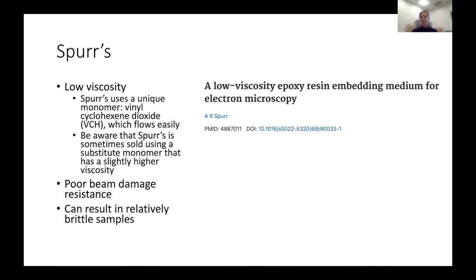So if low viscosity is very important to you, look into getting the original chemical instead of the substitute, because the substitute will be higher viscosity. Unfortunately, SPURR's does not resist beam damage very well, so it does infiltrate samples, but it will react to the beam. Also, SPURR's in my hands has occasionally resulted in very brittle samples, so it could be worth looking into including a plasticizer, whether it's dibutyl phthalate or an anhydride, just to make the block a little bit harder. Something to play around with, but SPURR's is excellent for a very low viscosity resin.